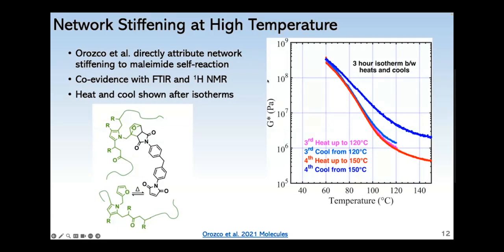I plotted G star, which is an overall indicator of the stiffness of the material, against temperature. So if you follow along some of their results, heating up, isothermal at 120 C, there's not much change. If you go up to 150 C, you see an order of magnitude increase in the material stiffness.